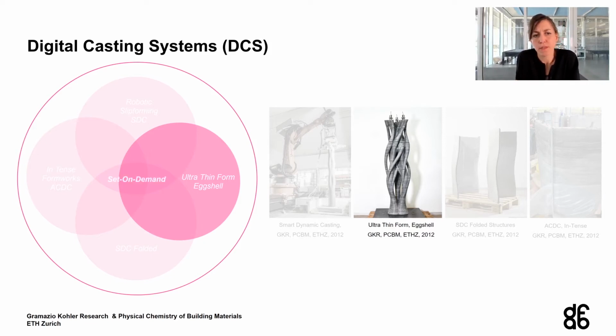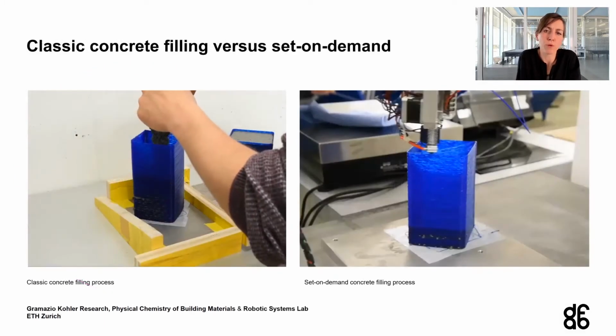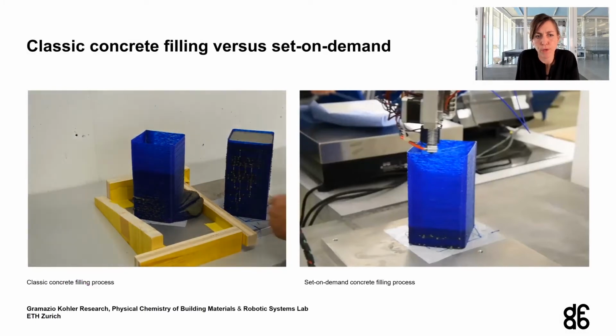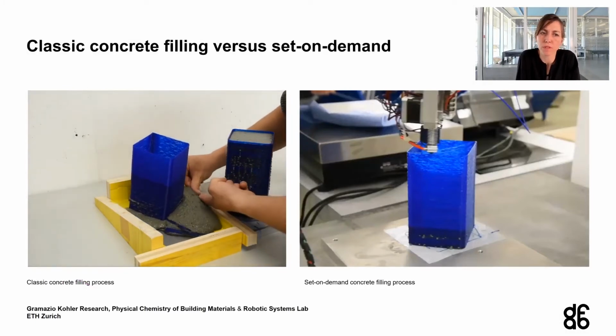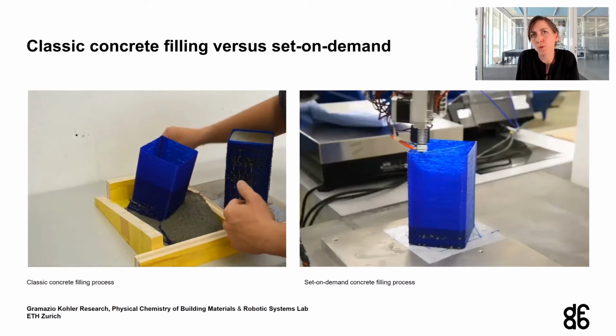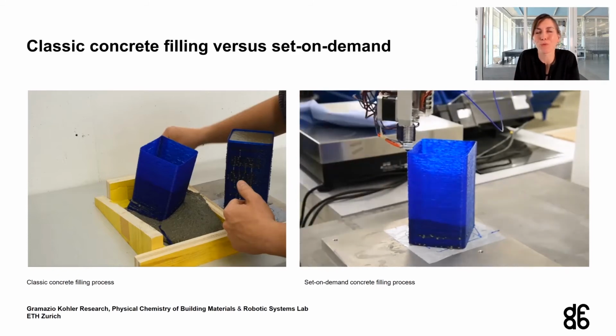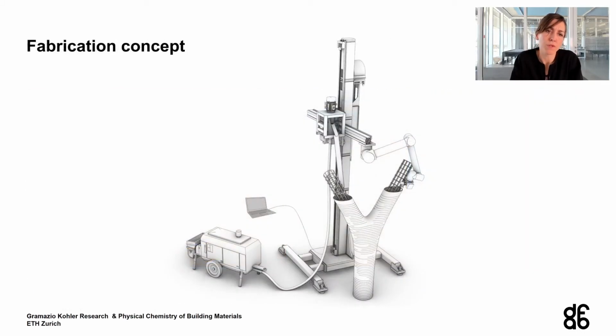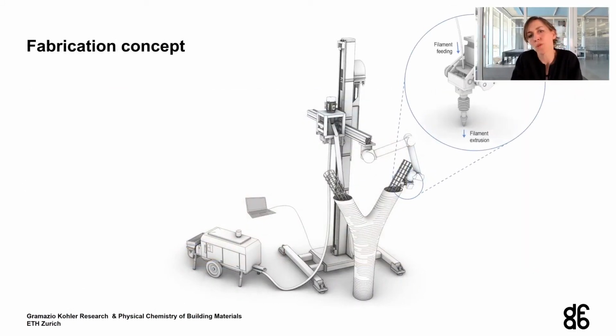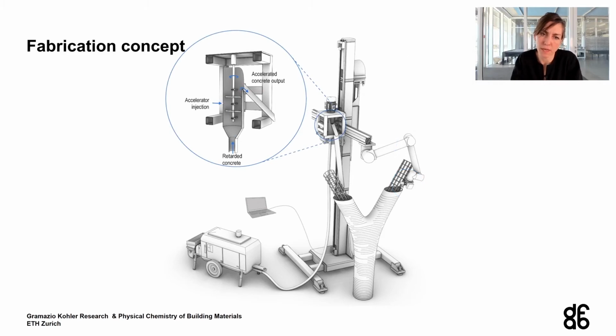So we asked ourselves, if set on demand with eggshell or ultra-thin formworks could be a novel way of thinking of the formwork. So in a normal classic concrete filling process of a thin formwork, the material would exert pressure and the formwork would explode, as you see on the image. But if you use set on demand, the material is not exerting any lateral pressure on the formwork. And we have a new way of thinking of a formwork, which is as thin as an eggshell, and thereby the name. So the fabrication concept that we developed was to use an extruder with a filament, which is printing as we fill accelerated concrete inside, and all this with reinforcement.